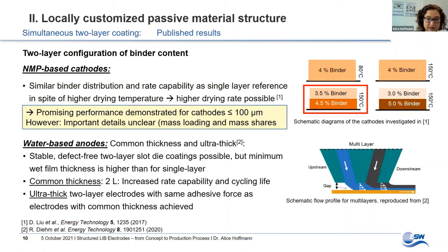There is also a study on water-based anodes, where a single layer and double layer configuration is compared for common thickness and ultra-thick electrodes. Here they saw stable, defect-free two-layer coatings, but the process window was limited. So the lower limit of wet film thickness increased, but there was no intermixing. So in principle, this two-layer coating was well performable.